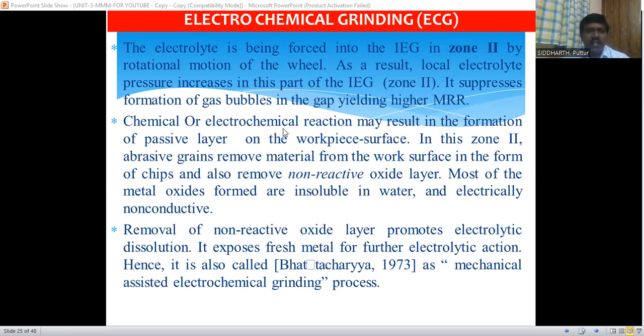The chemical or electrochemical reaction may result in the formation of a passive layer on the workpiece surface. So here one passive layer will be formed on the workpiece surface. So in this zone 2, abrasive grains remove the material from the work surface in the form of chips, and also remove the non-reactive oxide layer. So whatever passive layer is formed during this zone 2, that is also removed by means of these abrasive grains.